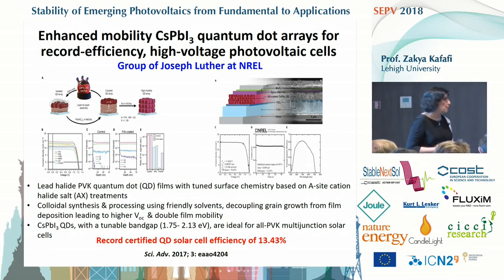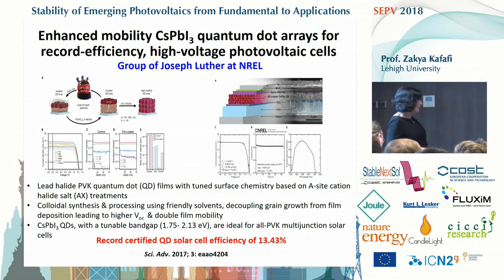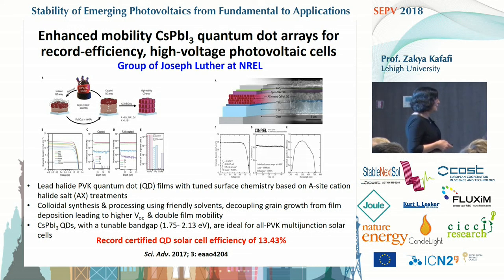double film mobility. So, for instance, the cesium lead iodide quantum dot had a tunable band gap between 1.75 to 2.13, which is ideal for all-perovskite junction solar cells, and they were able to get fairly high power conversion efficiency for these quantum dot solar cells.